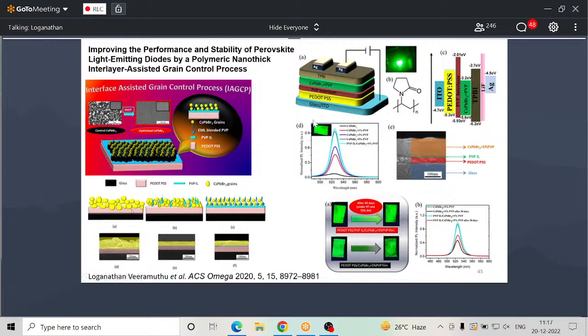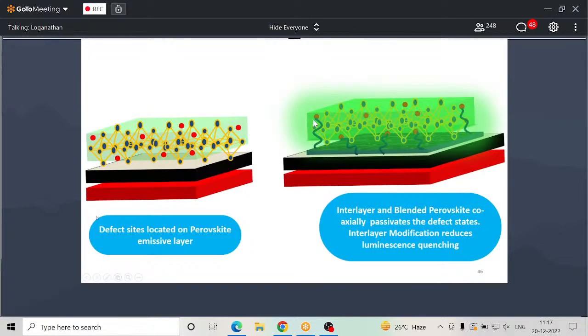So here in the schematic, you can see how we can improve our crystallinity, how we can improve the grain size quality, like that. We can also manage our stability up to 70% relative humidity. So they are stable up to 70% humidity. So it's quite good for the fabrication part. And this is the schematic in which we can see the defect sites located on the perovskites. The red dots are your defect sites. If we passivate those kinds of defects by using some polymers or some interlayers, that will enhance your luminescence by reducing your quenching sites.